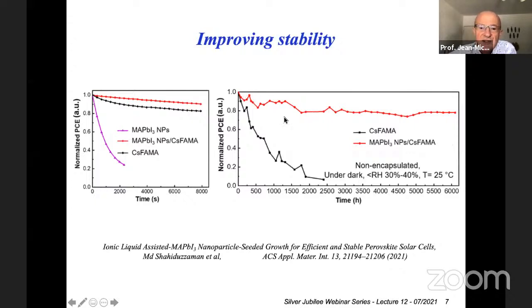Of course, it's a power conversion efficiency, but this is for storage over long periods in air without encapsulation, and under not very high, but humid conditions of 30%. Humidity, moisture is a principal cause of degradation of these materials, because they are composed of cations and anions. Methylammonium is a cation, or formamidinium, FA, also is a cation. Cesium also is a cation in that situation. And all of these are cations which can be degraded. I mean, not degraded, but swollen by water, which ends up degrading the perovskite material.